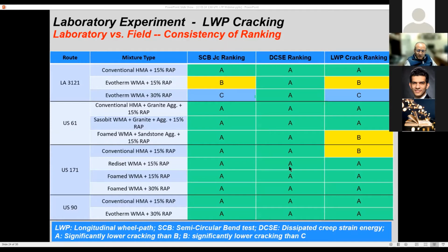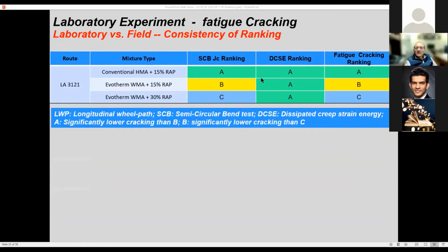In terms of intermediate temperature, we looked at the SCB-JC versus the dissipated creep strain energy versus longitudinal wheel path cracking. And you see that JC was able to correctly rank those mixtures. Again, this is ranking those mixtures for those test sections as similar to the field. And that's the bottom line: can the laboratory test rank what you are going to expect in the field? You see that in here, this section was not correctly ranked. This section was not correctly ranked. And then if we look at the same intermediate temperature cracking, you see that for fatigue cracking, SCB-JC was able to correctly rank those, as opposed to the dissipated creep strain energy, which was not able to.